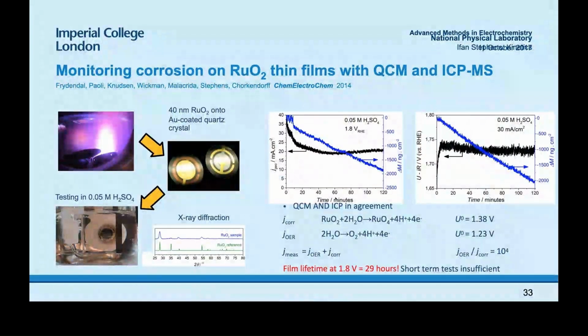So what this shows is that when you're trying to measure stability, if you only test the catalyst for 2 hours, purely electrochemical measurements are insufficient. You really need a separate way of measuring the dissolution rate. I would say the easiest and most versatile way is usually using ICP-MS. We've got facilities for that both in chemical engineering and in chemistry, measuring how much metal ions are in solution before and after the reaction.